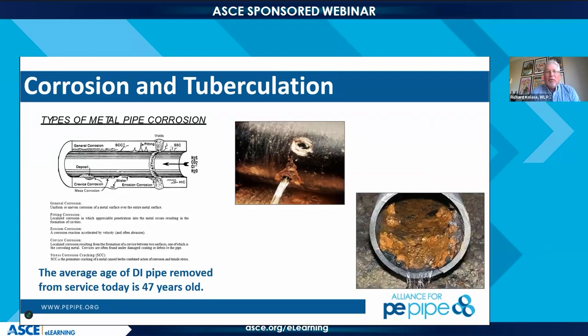So how does this happen? If you start doing a comparison between metallic pipes and polyethylene pipes, there's corrosion. The corrosion aspects of polyethylene do not exist. Unless there's some type of chemical that is attacking the polymer, that's not really corrosion, but more chemical attack. But you can see that legacy pipes do have corrosion issues. They also have tuberculation issues. Polyethylene does not support any biological growth, and things don't really attach to it. It's almost like a Teflon type polymer where things don't really stick to it.